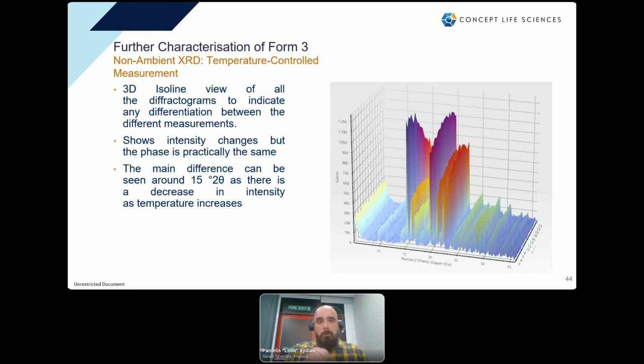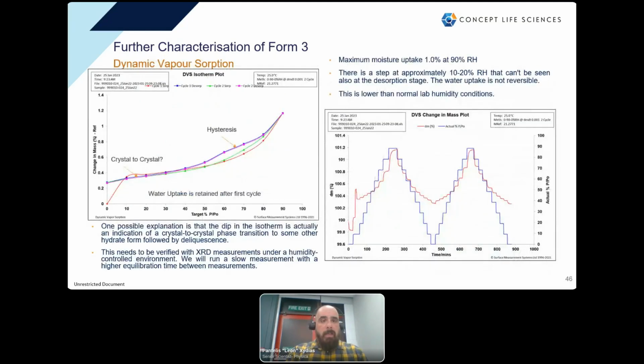But when we want to run some DVS measurements, we ran several of them. We had the material to do so. When we ran the DVS on the first cycle, we identified early on at approximately 10 to 20%, there is a small step on the isotherm plot. A small step that one of the possible explanations could be a crystal-to-crystal transformation.